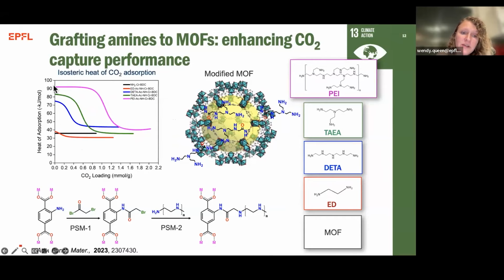So from there, we'll look at the isosteric heats of CO2 adsorption. This is simply the average binding energy at constant coverage. And so here, if we look at the parent MOF and then the material modified with ethylene diamine, what you'll note is that the binding energy is effectively very low.